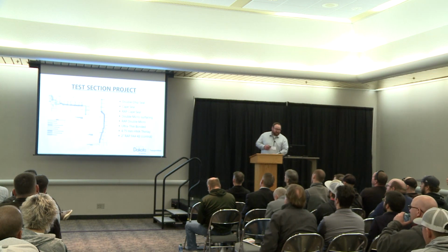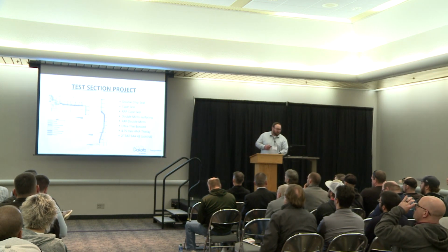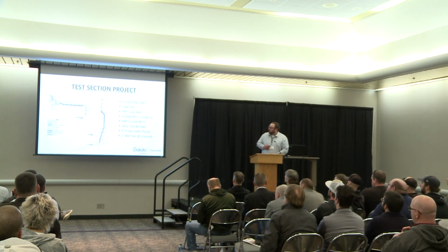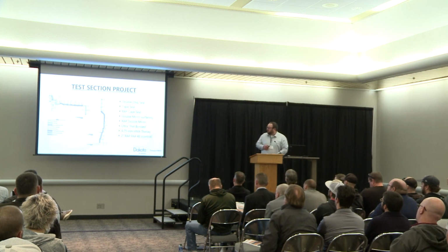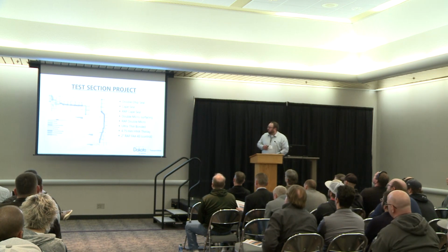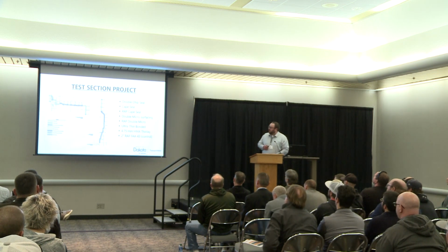So here's what we did on this test section project. Going from south to north, we started with a double chip seal, then went into a cape seal. And for those of you who don't know what a cape seal is, it is a chip seal with a micro on top of it. Then going into a wrap cape seal, a double micro, wrap double micro, ultra thin bonded wear course, a 4.75 millimeter HMA thin lay, which is similar to the 9.5, just getting even smaller, and a 2-inch wrap FAA 43 as a control.